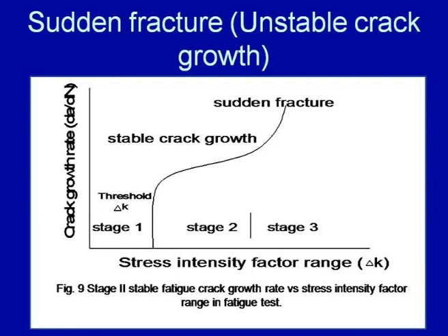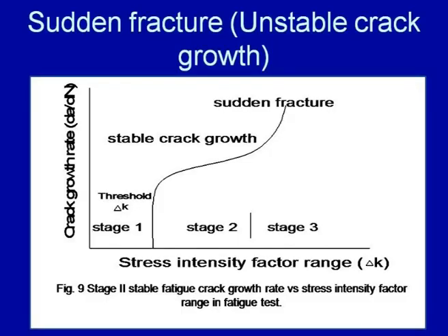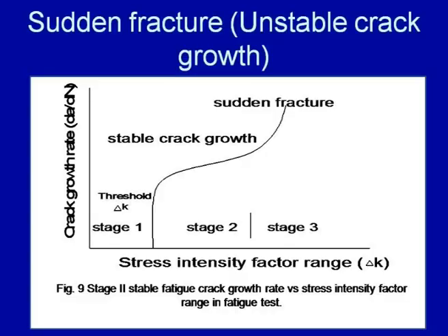If a crack is present in the component and the load is fluctuating, two factors are combined: the stress fluctuation and the presence of the crack, in terms of the stress intensity factor, which is composed of sigma root pi c. Here c is the half crack length for internal cracks, and for open cracks c is the crack length. So, we relate the stress range, the combined effect of the stress fluctuation, and the crack size present in the component, in form of the stress intensity factor